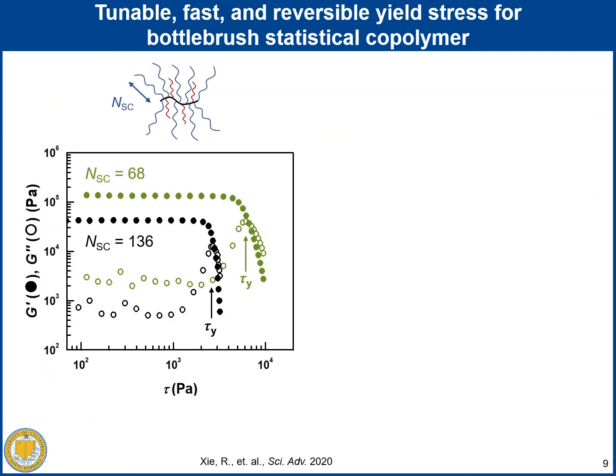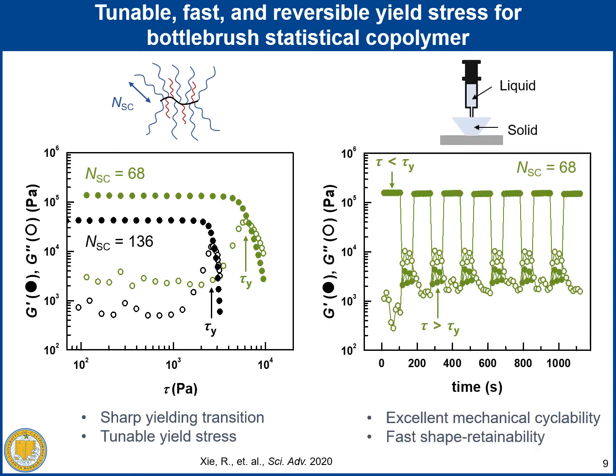Then the yield stress behavior is characterized by the oscillatory amplitude sweep, where a sharp yielding transition is observed when the stress amplitude exceeds the yield stress value. The yield stress, which is located by the G' and G'' crossover, can be tuned by the side chain length. Additionally, such yielding transition is shown to be highly reversible and quickly recoverable under multiple cycles of oscillatory shear across the yield stress.